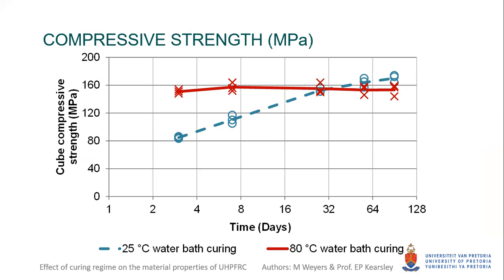The graph indicates that long-term strength development for concrete specimens is higher when cured in 25 degrees Celsius water than in the 80 degrees Celsius water. The cubes cured in the 25 degrees Celsius water show a gradual increase in strength up to 90 days. However, the cubes cured at 80 degrees Celsius reached a maximum strength of 157 MPa after 7 days. Thereafter, the strength slightly decreased up to 90 days.